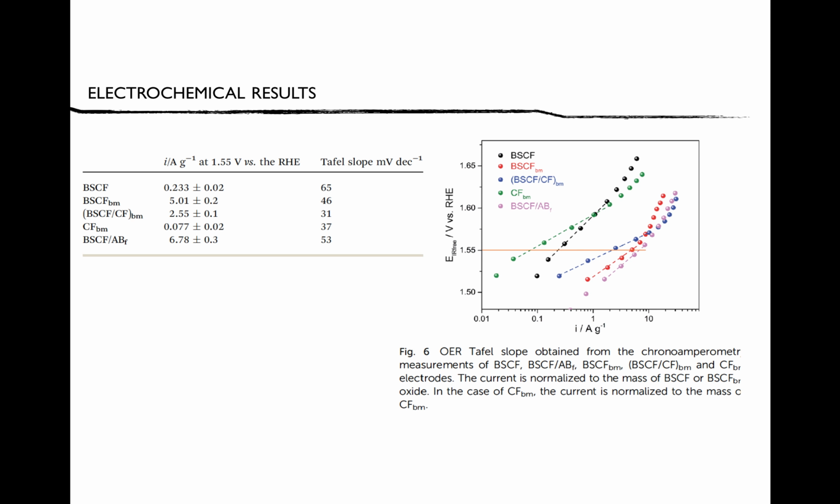In conclusion, ball milling of this particular perovskite will significantly increase its activity for the oxygen evolution reaction, and it stems from the formation of a surface layer with a short range order, and not necessarily simply because of a decrease in the particle size.